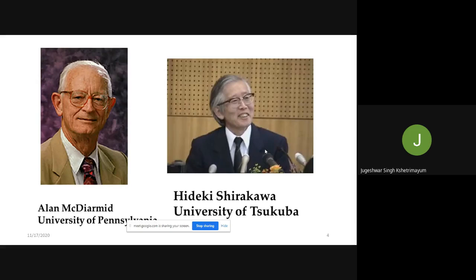Once they started working, Hideki Shirakawa prepared some samples. In that sample, they measured the conductivity and did elemental analysis. They found there was some impurity. They thought that if they removed the impurity, the conductivity might increase. Shirakawa tried to remove the impurities and make a purer sample of polyacetylene, but it gave a contradictory result. Instead of increasing, the conductivity decreased. Then they found something was contradictory.